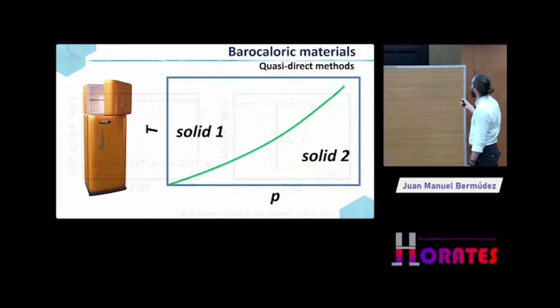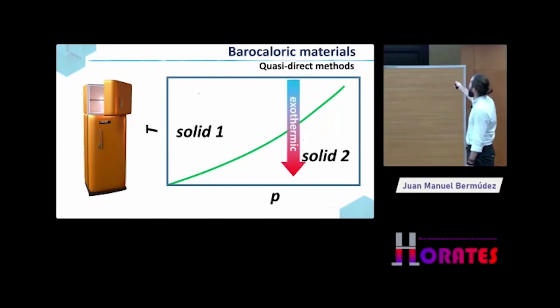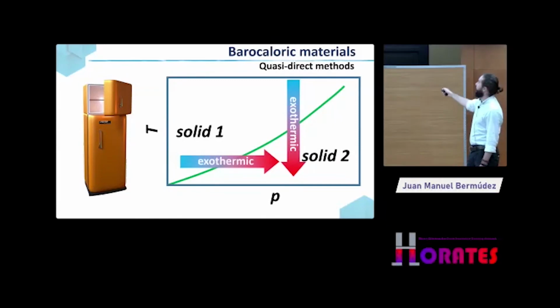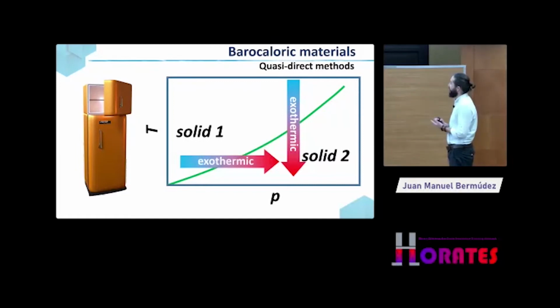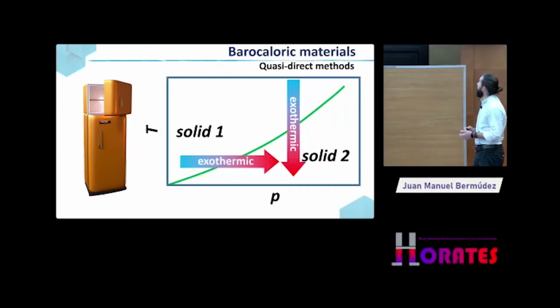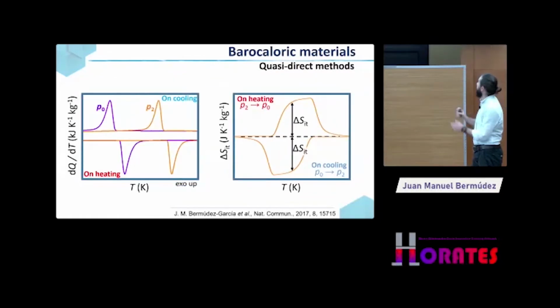But remember, we have done that on cooling, and if you go back to the solid phase transition, cooling down a material is an exothermic process because you start in the high temperature phase and go to the low temperature phase, so this exothermic transition releases heat, and that will be equivalent to applying pressure, which is also an exothermic transition. So in overall, cooling down is equivalent to applying pressure, and both are exothermic transitions that release heat, and this heat, we are not gonna use it for cooling. We just want to get rid of this heat, no? So the interesting part will be to characterize as well the reverse process, where you have the endothermic transition.